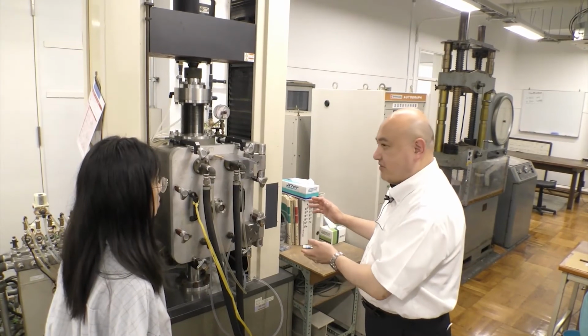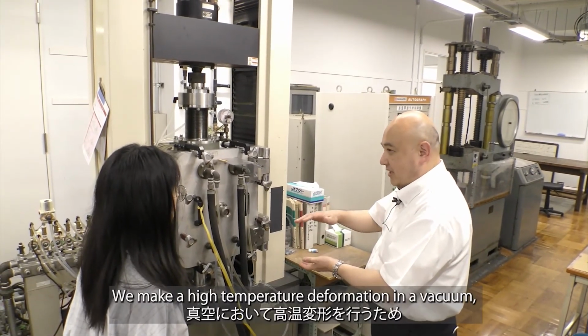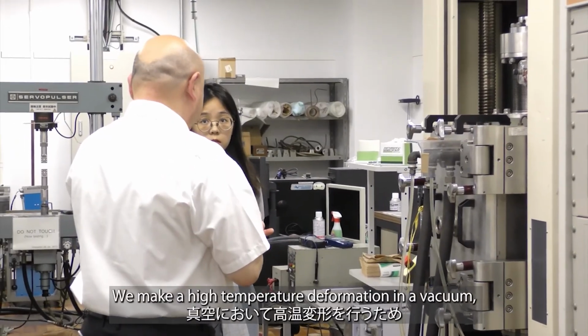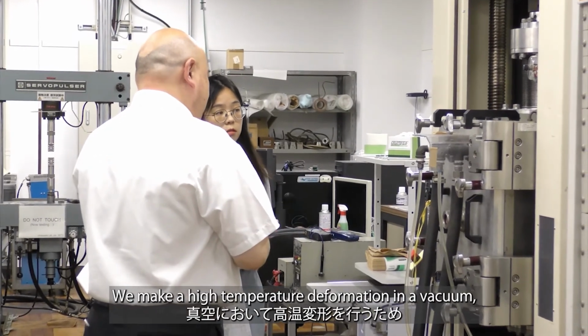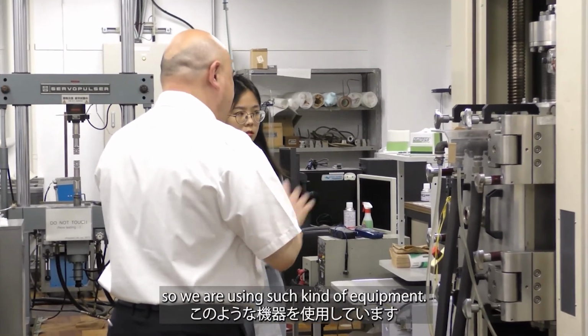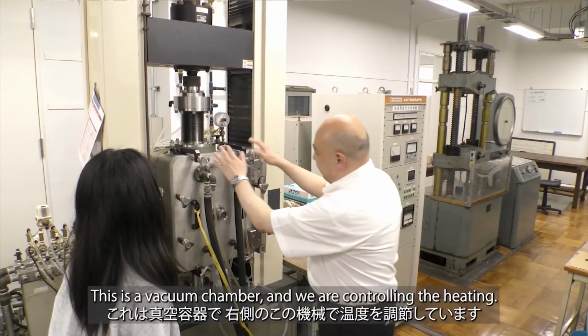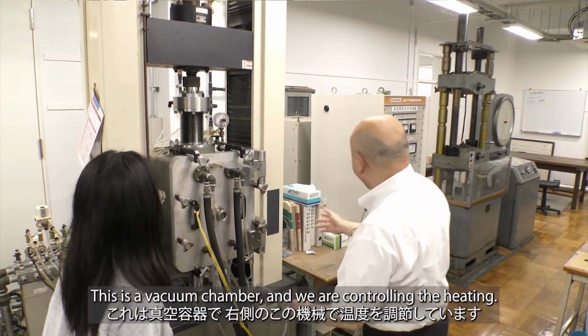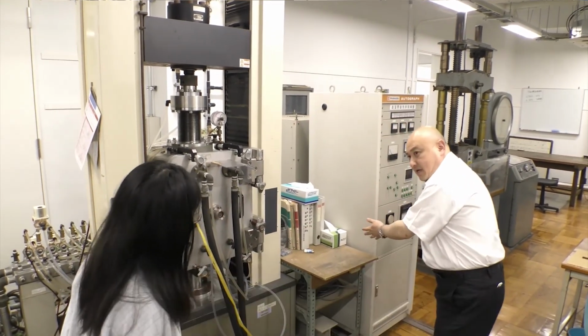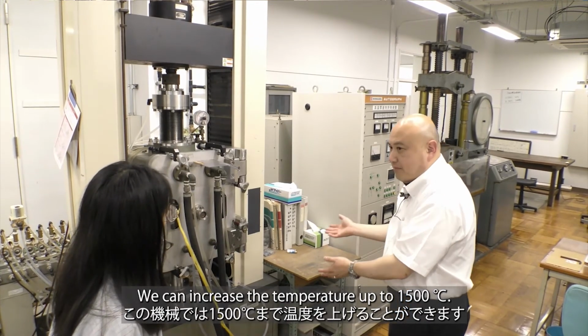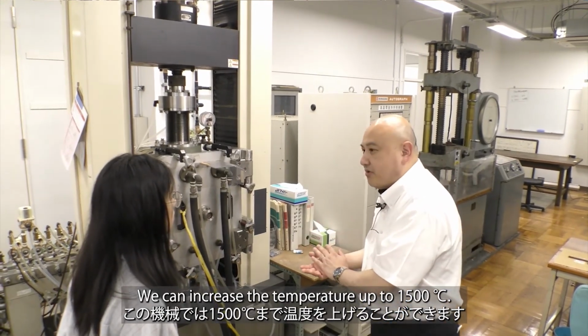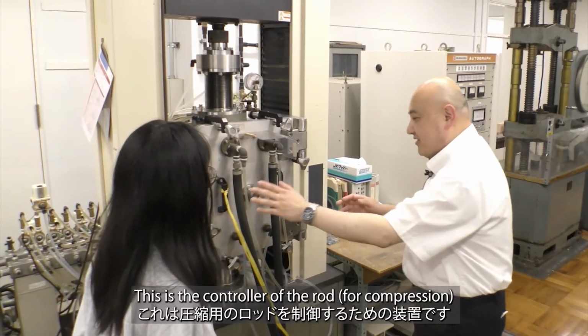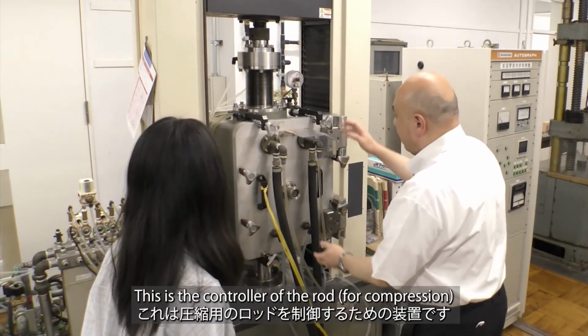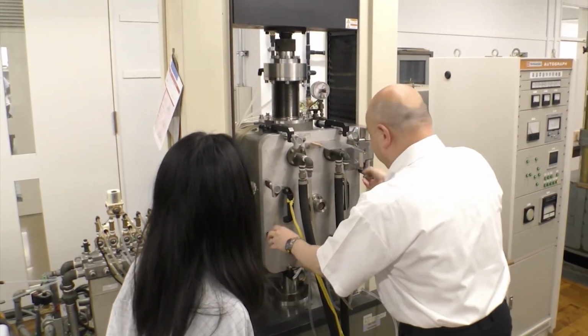Formerly, I have shown you that we make a high temperature deformation of this in the vacuum. So we are using this kind of equipment. This is a vacuum chamber, and we are controlling the heating. We can increase the temperature up to 1500 degrees C. And this is the controller of the rod.